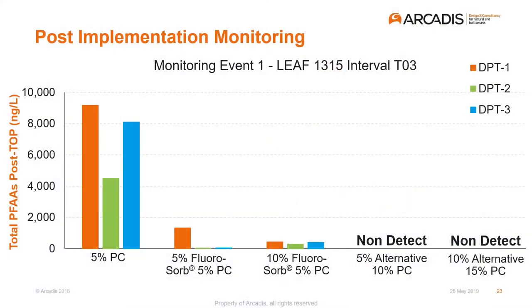The concentration on the y-axis is in parts per trillion. All the different formulations are shown along the x-axis, and we had three direct push points from each test pit. And the alternatives came back with non-detect so far. The control, which was just the 5% Portland, is pretty consistent with what we saw during the initial assessment.